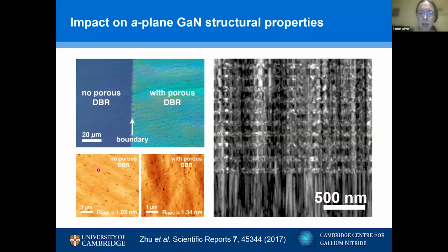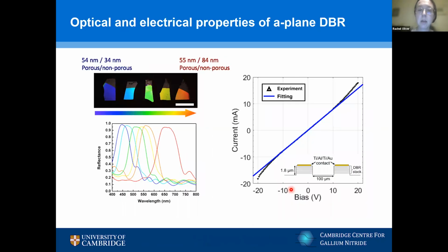Key thing is that after we've formed the porous DBR, we've still got a fairly smooth surface. A-plane surfaces are not as beautifully smooth as we get on C-plane anyway, but we have a very similar RMS roughness, not much change to the surface morphology at all. And we can see there's a lot of defects in this TEM imaging cross-section, but we're not seeming to do much to the defect density either. It's not great material, but we're not making it any worse.